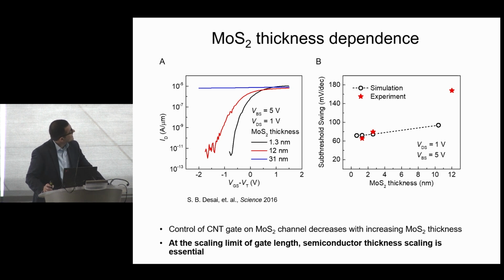Now, to just highlight the sensitivity on the thickness, we built different devices with different molybdenum sulfide thicknesses. So 1.3 nanometers, that would be bilayer, that's what is shown here. 12 nanometers, that's the red one, and the blue one is 31 nanometers. So if molybdenum sulfide is 31 nanometers thick, there is no current modulation by the gate. You have a perfect resistor. And even for the case of 12 nanometers, you can still have a good gate modulation. Granted, the subthreshold swing is worse.